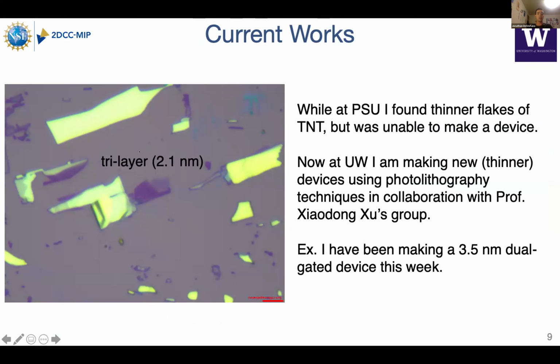And so now, current work: I found thinner flakes at Penn State. The thinnest one I showed in the last slide was 9 nanometers, but I actually managed to see a trilayer a few times, which is about 2 nanometers. But unfortunately, due to the geometry restrictions of the pre-deposited contacts I was given, I was unable to make devices with these. But now at the University of Washington, I'm working in collaboration with Professor Xiaodong Xu's group, who is really at the forefront of this kind of 2D stuff. And we're using some fancy photolithography techniques to actually make devices with these thin flakes. For example, this week I've been making a 3.5 nanometer dual gated device, which should allow us to see some more interesting stuff.